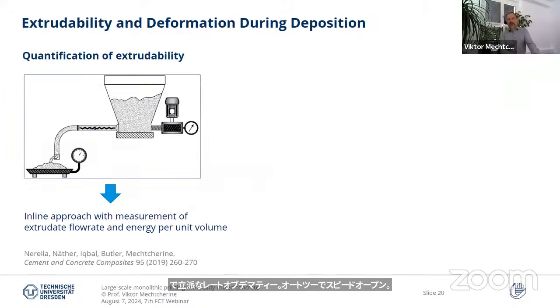Good. So at the end of the day, what we can suggest is that for every extruder which is attached to this kind of mobile pump or any other equipment you use in extrusion-based 3D printing, you best measure inline the energy which you need per unit, so volumetric unit or weight unit, of concrete extruded. It's the first thing. Then you have this relationship between the extrusion rate and the energy needed for a specific device, but you also look at the quality of the concrete coming out of the nozzle. It should be a steady flow without any interruptions, etc.